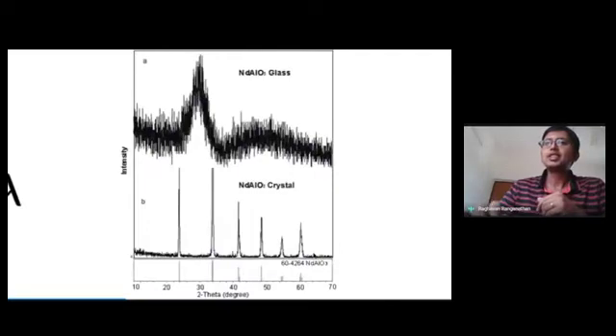Okay. And the interesting thing that people found is when they characterized X-ray diffraction of these glassy materials. I'm showing one such example where we have a neodymium aluminum oxide glass and an equivalent crystal that can be formed from this material. We see that the crystal exhibits very sharp peaks, and these profiles are very well distributed at specific 2 theta angles. All right. And if you look at the glass on the other hand, it obviously lacks this periodic order, the information that's captured in this periodic order. So that gives the basic hint that glasses do not have any long-range periodicity that crystals exhibit.